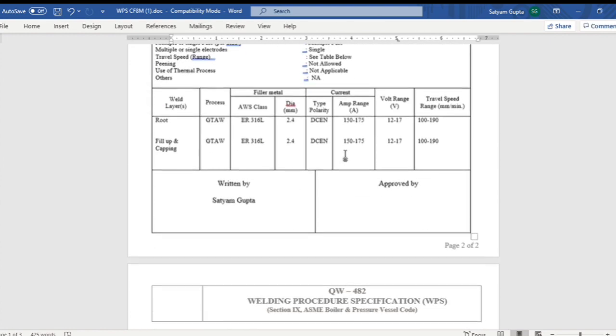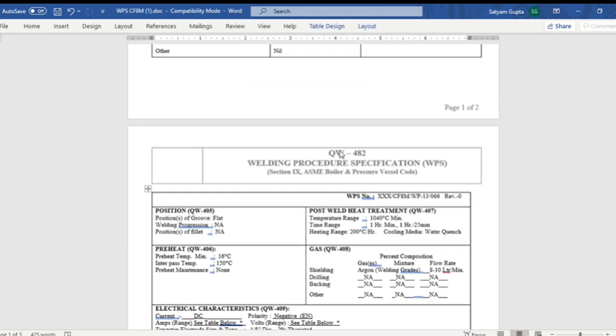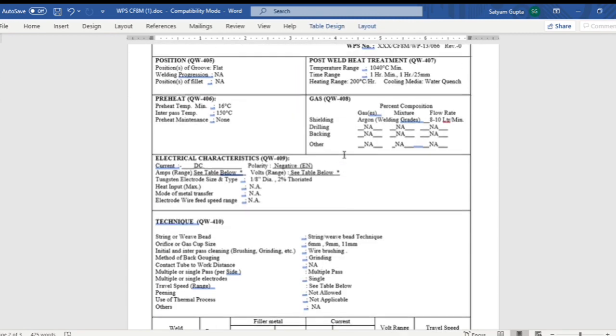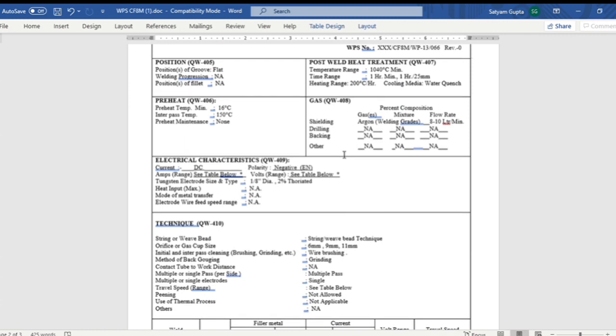Now I will move to the next page where you can find some more essential data, like position, QW405. You can see the position of the groove is flat. So the welder can perform only flat welding or groove welding. Now QW406 is talking about preheat temperature and interpass temperature. Preheat temperature before starting the welding, the minimum temperature shall be 16 degrees. It may be more than 16, like 30 degrees, okay, 40 degrees, okay, 50 degrees, okay, but not less than 16 degrees. If the temperature is suppose 0 degrees or -5 degrees, then we need to preheat the component up to a minimum of 16 degrees.